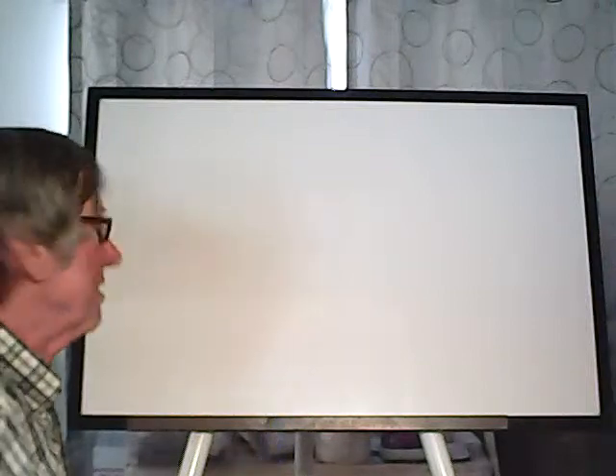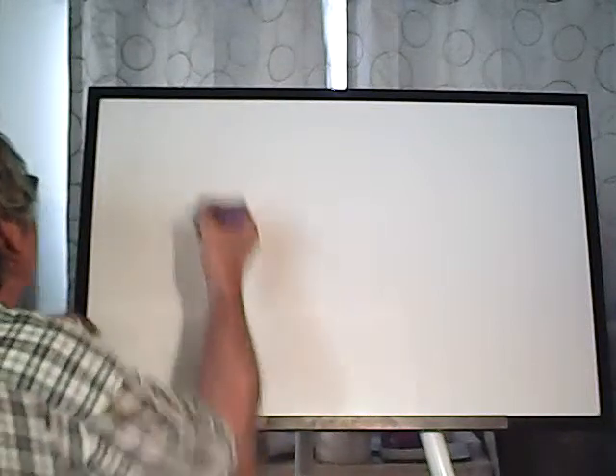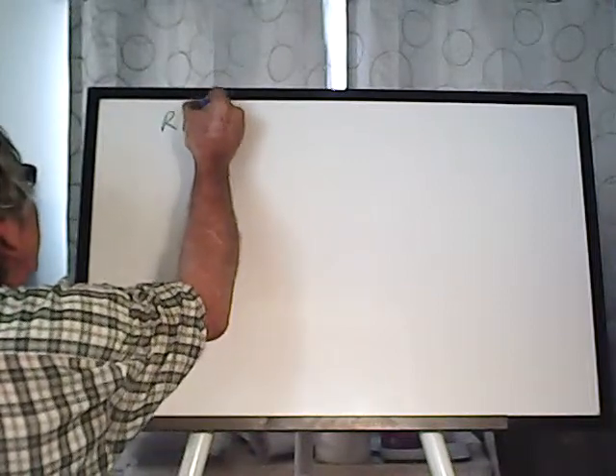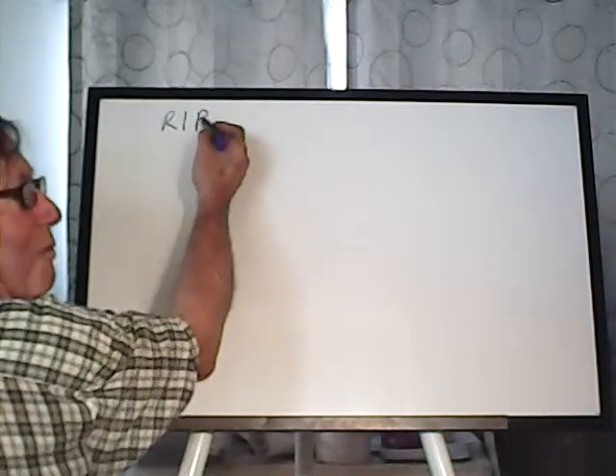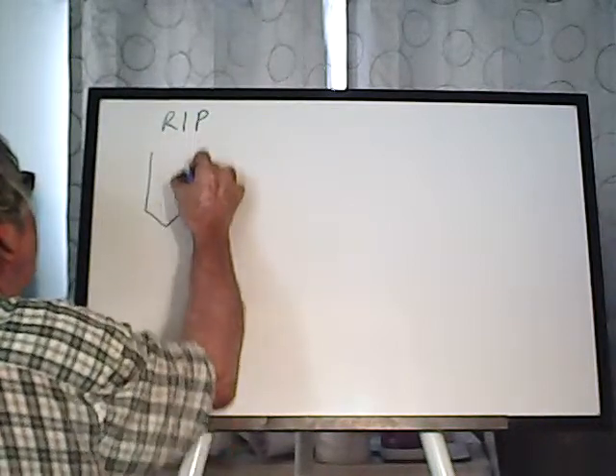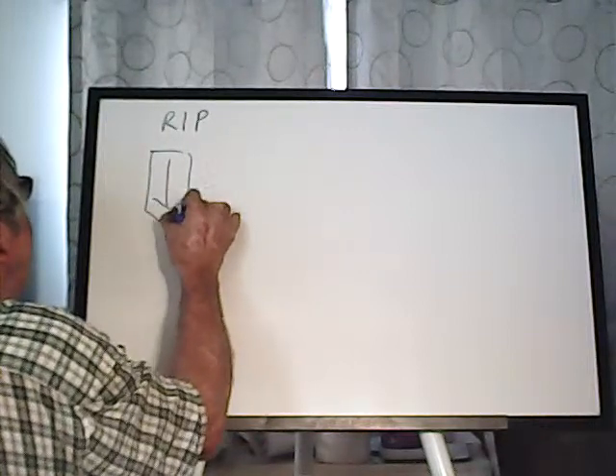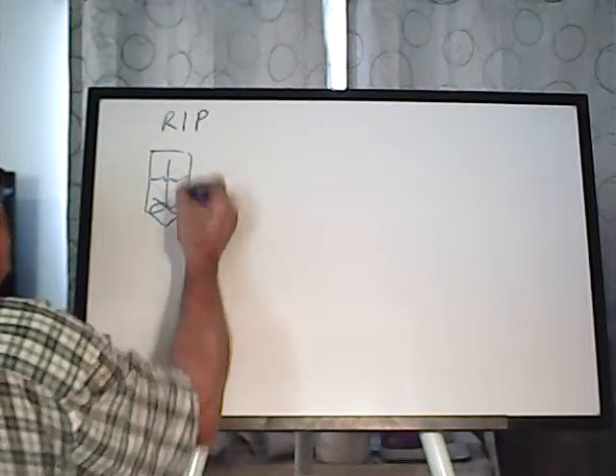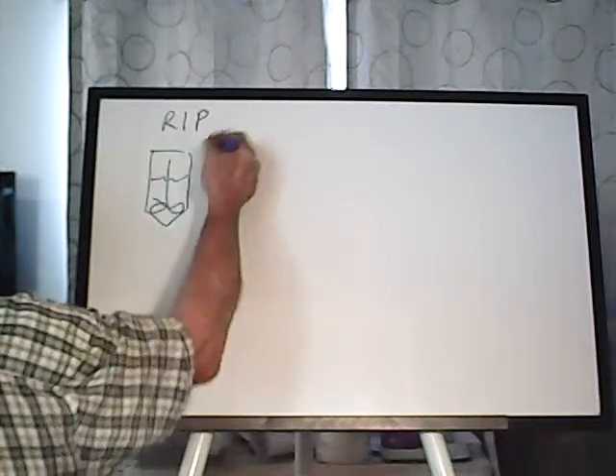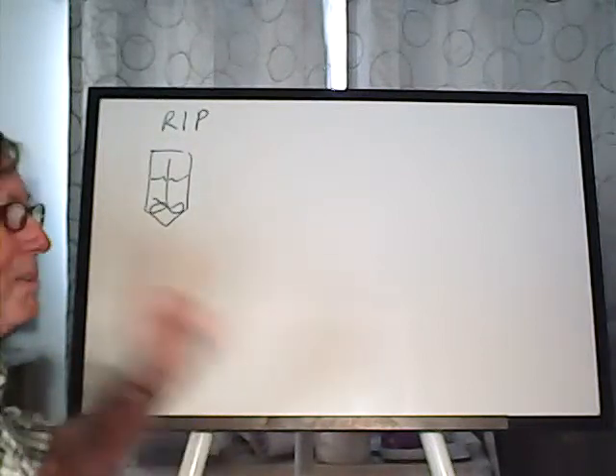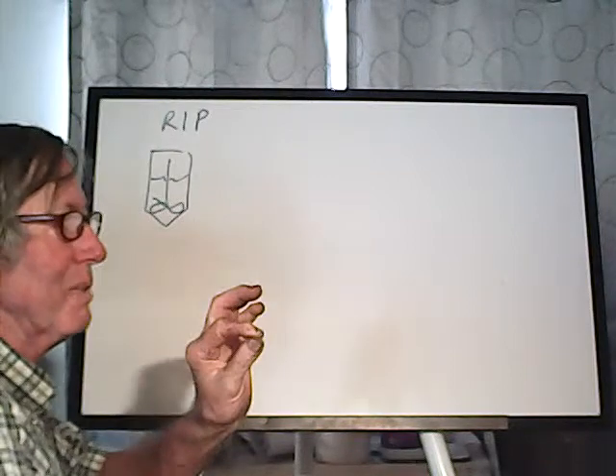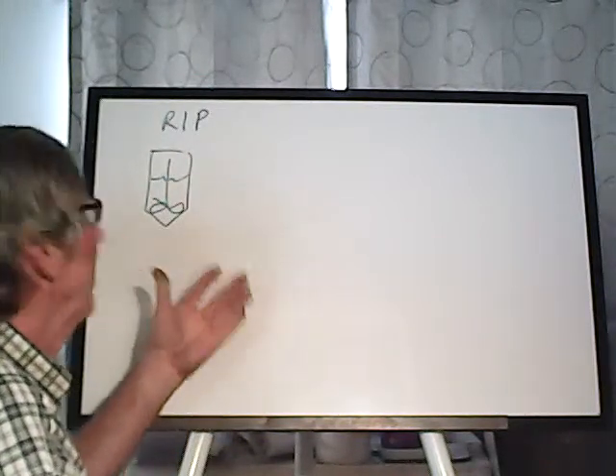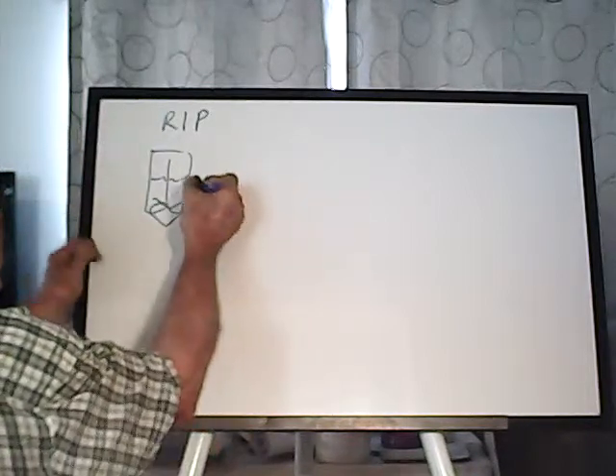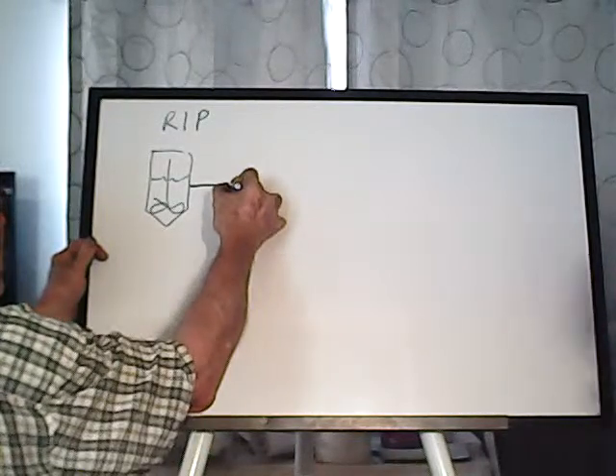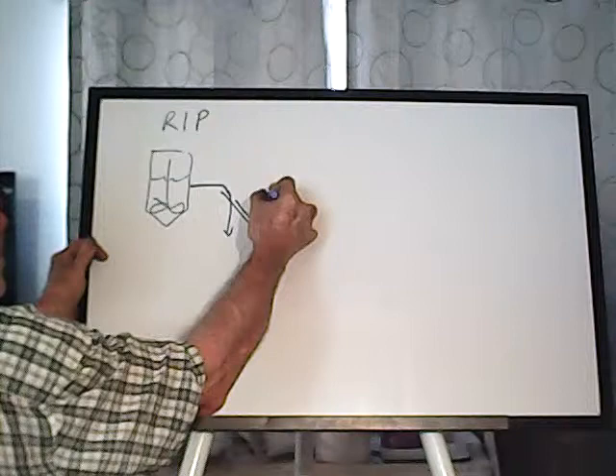adsorption. Okay. Now there's three different ways of using the resin. RIP, and that just sounds bad, stands for resin in pulp. And you have your tank. It's got an agitator. You've got your slurry, and you add ore, resin, and solution at the same time. The ore has to be ground significantly finer than your resin beads, which normally isn't a problem, right? So that when you're done leaching it, screen out. This goes out, you just have a screen, and the slurry goes through, and the resin comes off here.